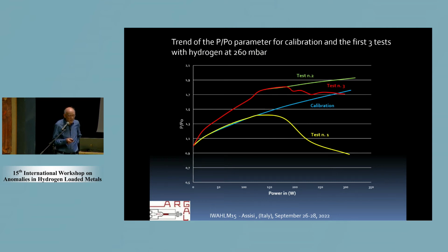And the second test, the green line, is visible only at high temperature; the pressure was increasing since the beginning of the experiment. It means that the hydrogen absorbed was desorbed into the reactor. And at a certain point, you can see that the increase of the pressure is much less.